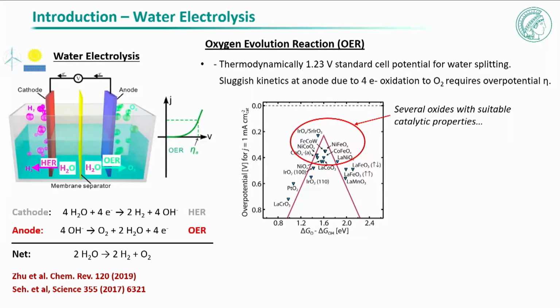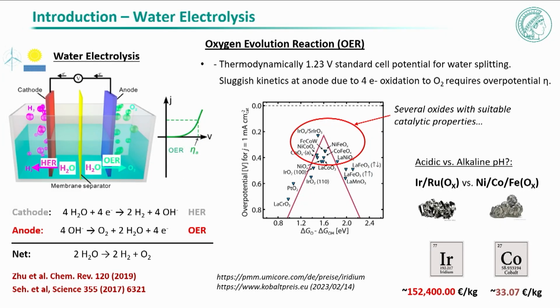But we know by now what to do and what are the materials that are working. There is a lot of theoretical and experimental work, and we know that there are certain mixes of oxides, iridium oxide, and mixes of nickel, iron, and cobalt that are going to be very good catalysts for this. Ferdi mentioned that there are two technologies, one in acidic and one in alkali. And the problem is that the one that is very efficient, the acidic, works with iridium oxide, ruthenium oxide. Just to give you an idea, 152,000 euros per kilogram. And you don't have iridium everywhere. So if you want to do a global energy conversion and you want to use PEM fuel cells, then I think you are in trouble, because we don't have enough iridium. It's extremely expensive, and it's not everywhere.